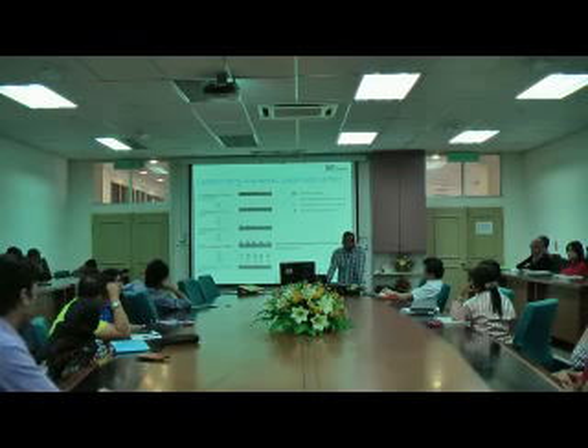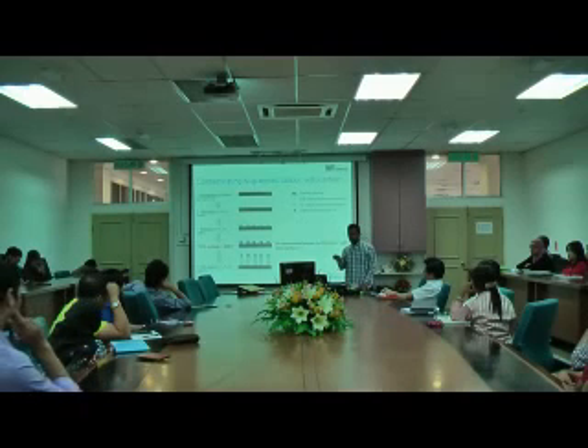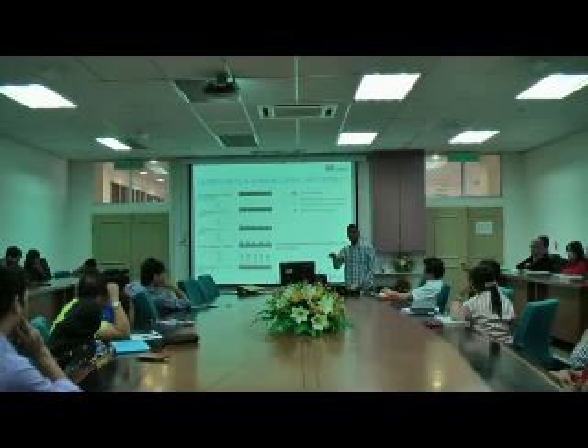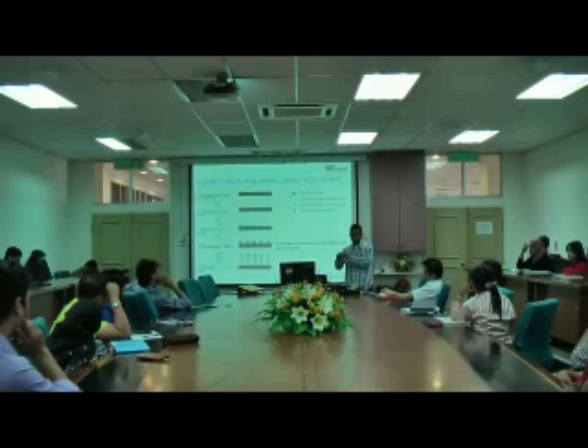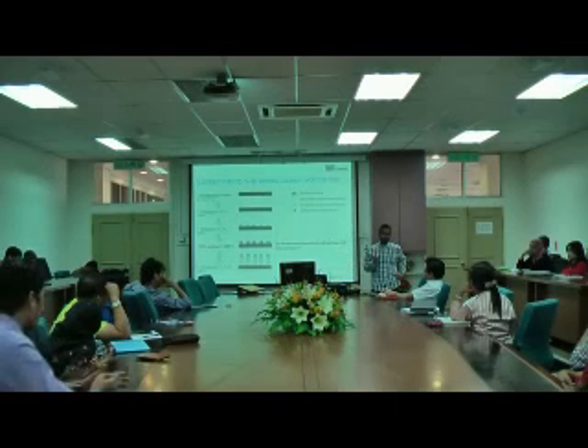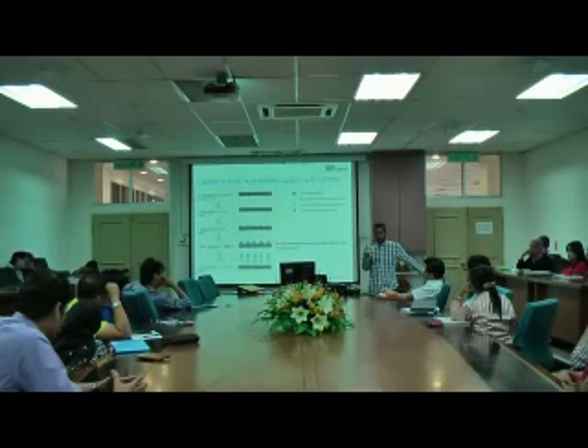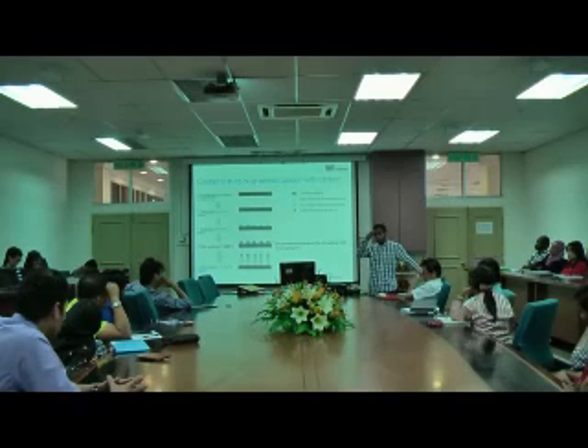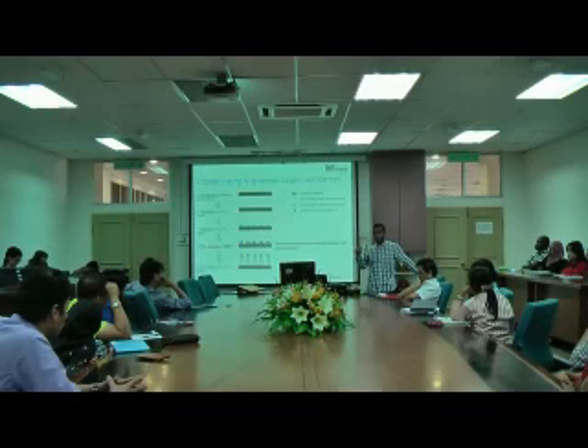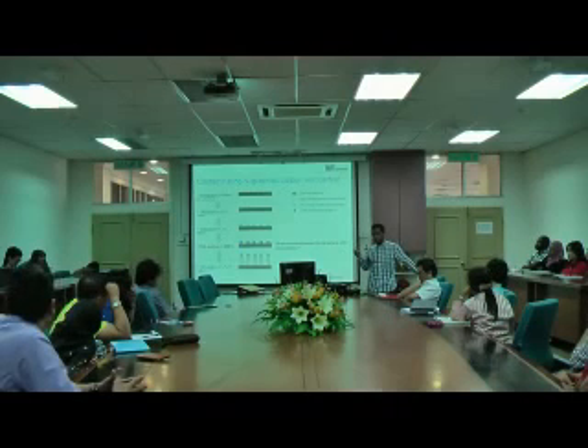Why do you choose nickel? The nickel is a very simple system. Iron has iron 2 and iron 3 and its structure is rather complicated. It has a stable carbide structure, so there exist different types of iron carbide. And we want, again, the keyword is always simplify the problem. Nickel forms only one type of carbide, hexagonal nickel carbide, and that is decomposed at 300. So the only possibility here is dissolved carbon. So in this case, nickel is simple.